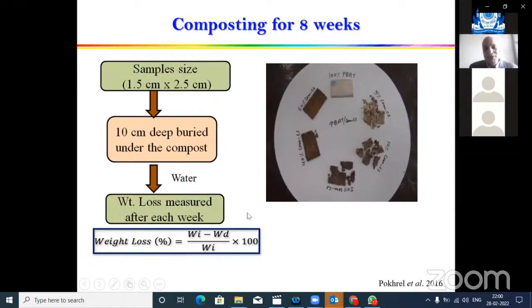So what we see is this: this is the 100% polymer, this is the composite with 5%, this is 10%, 20%, and 40%. After 8 weeks, we see that most of the composites disappear inside the soil. Sometimes it was difficult to find the samples that had been inserted into the soil.